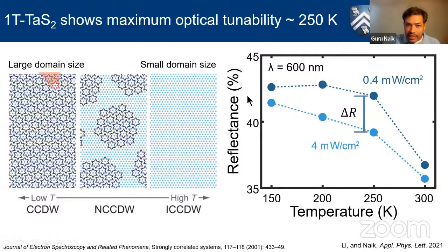What we saw here is again reflectance at one particular wavelength plotted as a function of the temperature of the sample. At room temperature, we see some. As we reduce temperature, the reflectance change goes up. But as we go to further lower temperatures, like the commensurate phase, which is where the whole layer is condensed into a CDW domain, we still see tuning, but it's small. We still see tuning. So that was surprising.